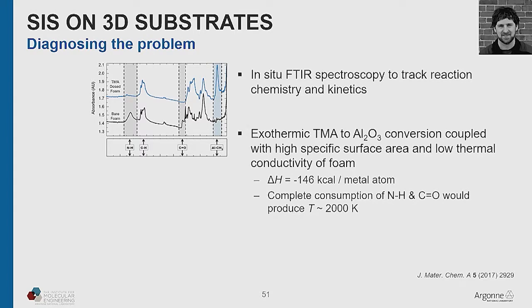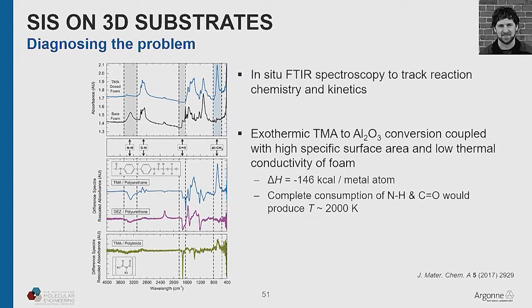Now you can just do a back of the envelope thermodynamics calculation here. So those are exothermic reactions of TMA consuming those groups. And if you consumed all of the available groups that you estimate are there and no heat left the foam, of course some does leave the foam, but if none did, the temperature would rise to 2,000 degrees. Hence, it's gone. So what can you do about that? If that was the end of the story, I guess I wouldn't be telling you the story. So there are a number of strategies that allow you to get around this problem.